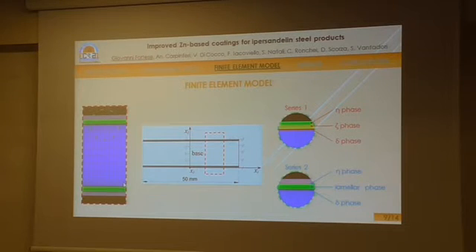A finite element model is proposed in order to numerically simulate the bending behavior of specimens. In particular, considering the hypothesis of plane strain condition, a two-dimensional model with 4-node plate finite elements is employed. Due to the symmetry, only 1/2 of the specimen is modeled. And in order to adequately simulate the experimental boundary conditions, the following ones are considered.